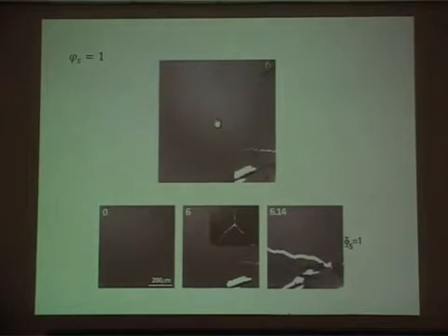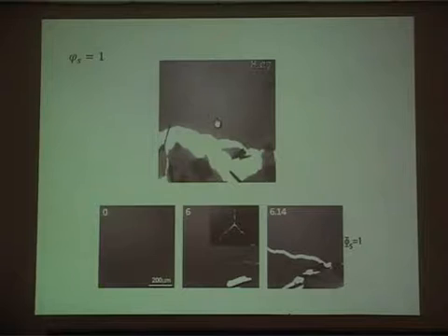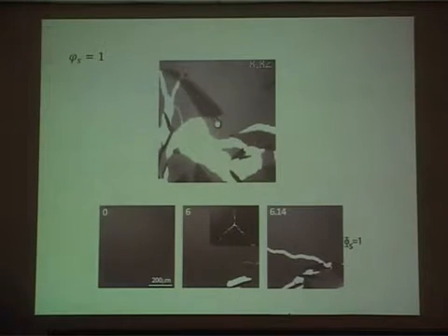So what you saw previously was single particles popping out, and now what you see is basically chunks which are coming out. That is the field, what you see on the top up here, and now you see this whole thing coming off as they're breaking off into length scales, and they're just leaving the substrate. This is just because the flakes go out. It's a finite size system. To minimize its torque, they want to flip in this direction.